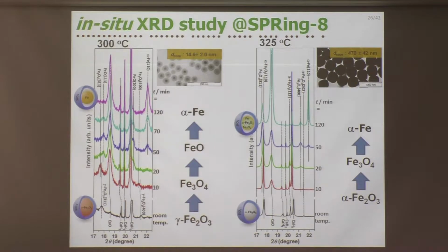Here shows the results from other samples, which have a bigger particle size, and the starting phase is alpha iron oxide. However, it is reduced to Fe3O4 and finally to alpha iron. If we compare these results, you may feel the reduction processes are very similar.